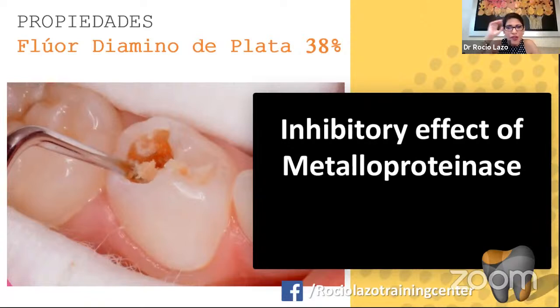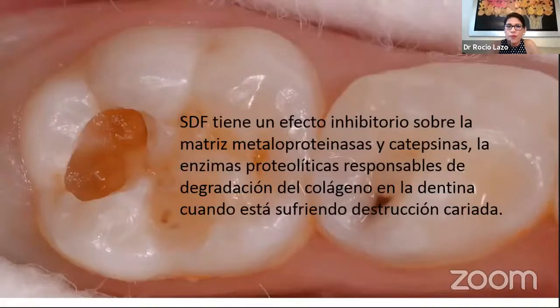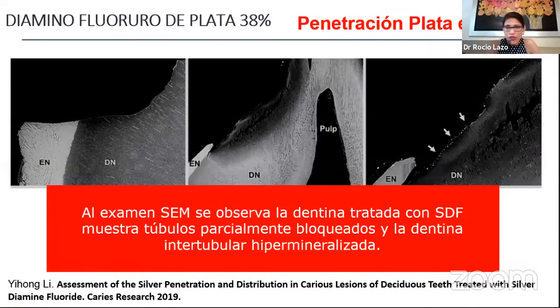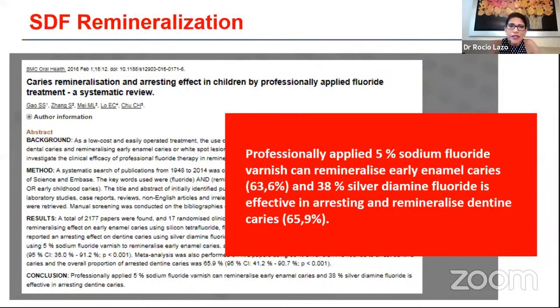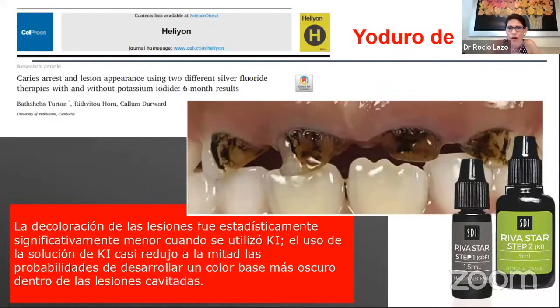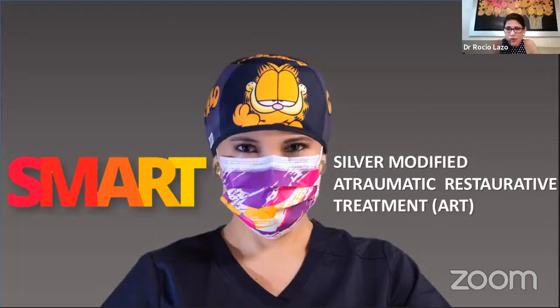Do you remember the metalloproteinases that we are crazy about, because if we add orthophosphoric acid, we're going to wake them up and this will degrade the adhesive. Okay, an inhibitor of this effect is the SDF. The penetration of SDF in dentin is great. It's better than in enamel. And for that reason, this systematic review suggests that for enamel it's better to use varnish, and for dentin it's better SDF. But my problem is not the color. The color is not going to be a problem if you put the KI, you're not going to have problems, okay?